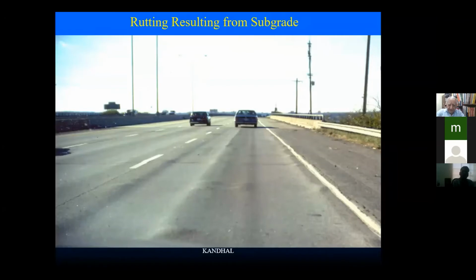Because the way the rutting is taking place here is very abrupt. There is no bitumen flow. It's not very smooth. And sometimes there might be some cracks in here also. But this I would say is because of the subgrade, and especially you can see there's a bridge here. When we do the approaches of the bridge, they are done last, and sometimes we don't do a good job of compacting the subgrade. So this kind of rutting will occur near the approach to a bridge, on both sides. But again, you can identify the problem by doing some more exploration. I'm just showing you a picture which can sometimes give some hint why the rutting is taking place.